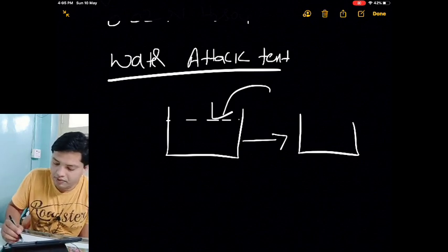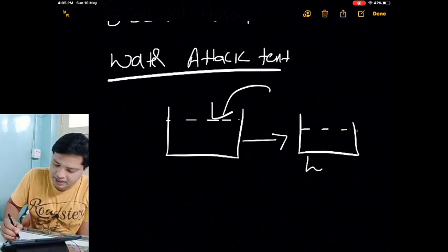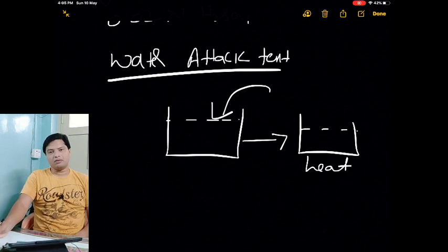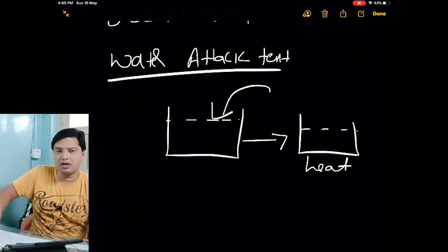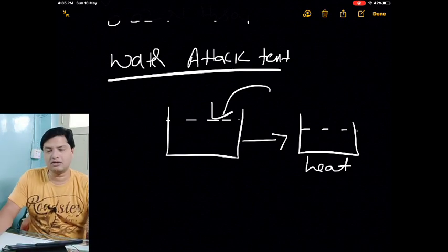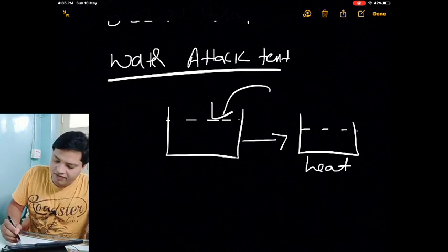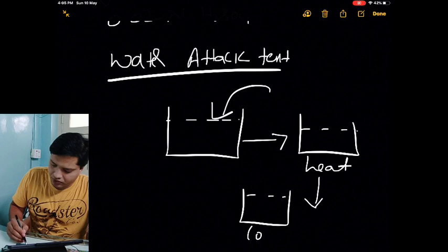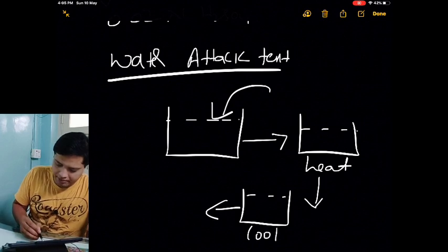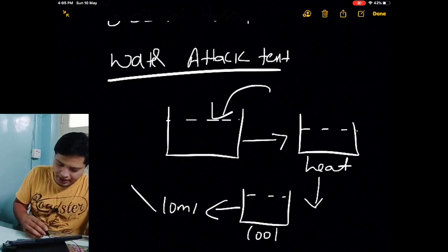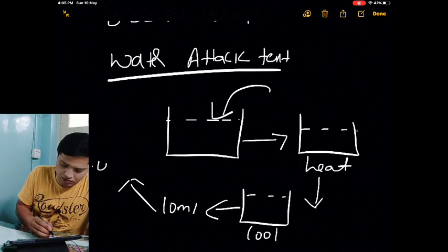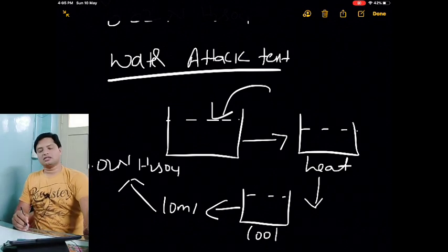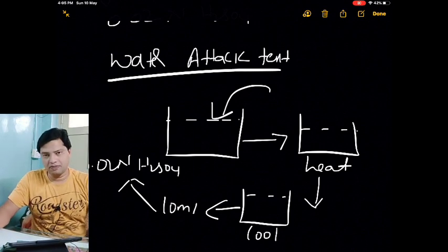After filling to 90%, heat it at 100 or 120 degrees for 30 or 40 minutes. After heating, cool it again under tap water. Then take 10 ml and titrate this 10 ml with 0.02 normal strong acid. Then you will get some values.